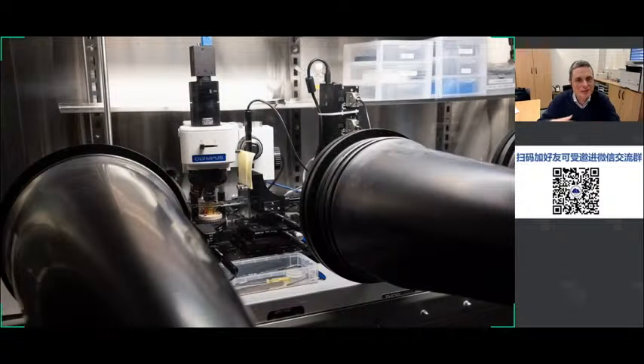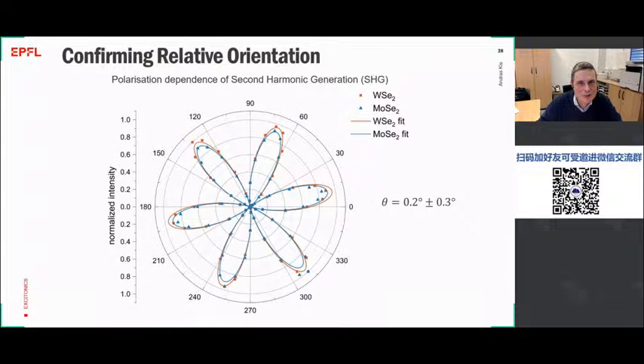And once you build such a heterostructure, then it's also important to confirm the relative orientation between the different layers. This we can do, for example, using second harmonic generation and the polarization dependence, and then we can measure what is the relative orientation between the different layers, because the relative orientation is going to influence a lot the probability of transition between the different K points in the different materials, and also the landscape for the Moiré potential that can influence the motion of excitons.